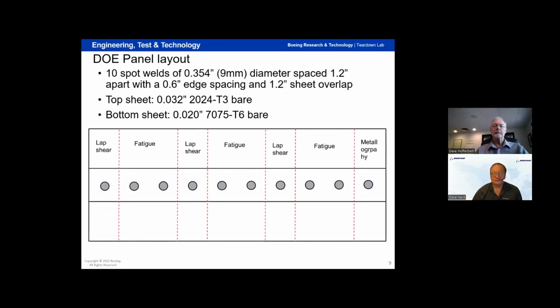We're trying to keep a lot of the same parameters when you're doing a rivet replacement. So keeping an edge distance, looking at your overlap and your spot spacing. So these all equate to at least 2D and 2D for edge and sheet overlap, as well as a 4D spot spacing. Again, for a 032 to 020, so pretty thin material. So it can be susceptible to a lot of the other properties that we're messing with. So just to showcase, as we're stepping down to do the lap shear and the fatigue.